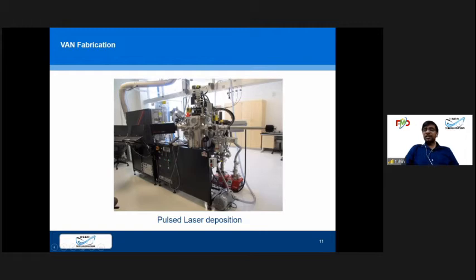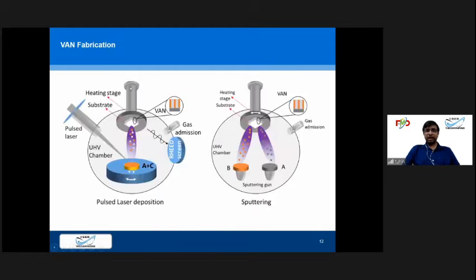The substrate is heated to a very high temperature of 600 to 800 degrees Celsius, so that when the atoms are deposited on the substrate, they get enough energy to form the crystal which we want to make. So this is the schematic diagram of pulsed laser deposition. This is the substrate holder. We heat it according to the temperature we need, say 800 degrees Celsius. And the laser is coming here. And this is the material we want to deposit. We make a target out of some chemical composite, raw powder or something, and make a pellet out of it.